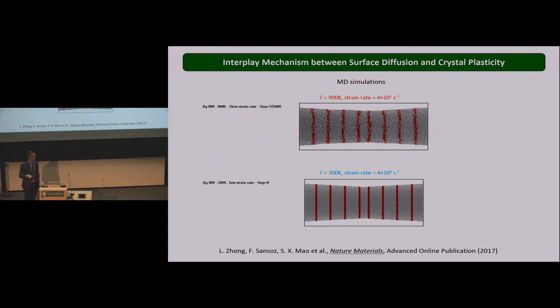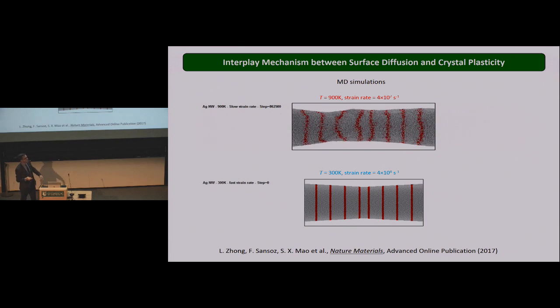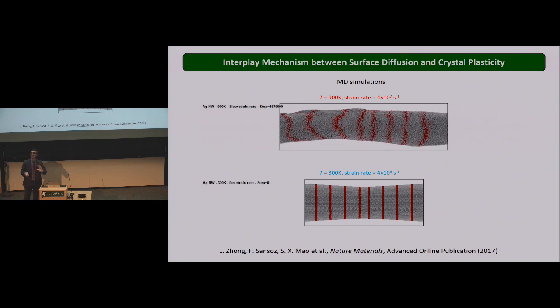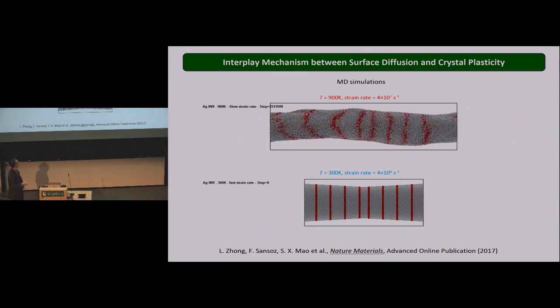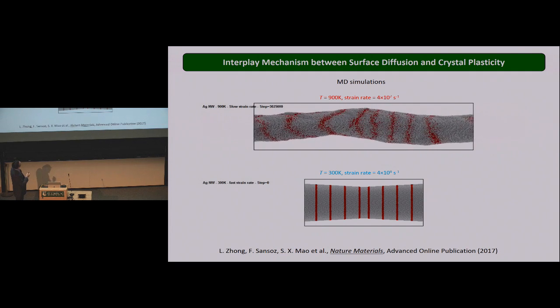Now, to verify that, we conducted some atomistic simulation. The way we do that in atomistic simulation, we change the temperature to control the surface diffusion. Right? Because it's very hard, the time scale is so short in simulation to simulate diffusion. So here there's high temperature and slow strain rate. And you see the atoms here get diffused more easily on the surface.